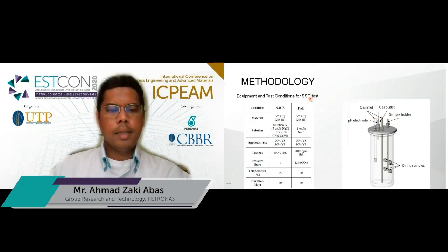For the SSC test, the NACE standard is TM0177, Method C, the standard ring test. Solution A is based on 5% sodium chloride and 0.5% acetic acid. The test is 100% H2S, 1 bar partial pressure, temperature 25 degrees C, duration 30 days. And for the field test, the solution is 1% sodium chloride with 2000 ppm H2S, pressure 120 bar CO2, temperature 80 degrees C.